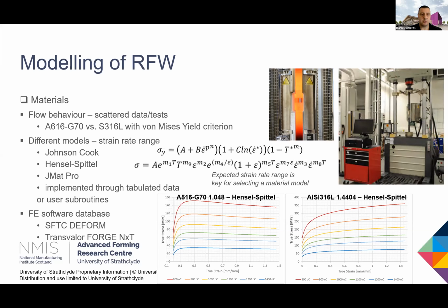However, we can generate material properties from software like JMatPro and implement them through tabulated data or use subroutines. In this specific work, we used information from the software SFTC Deform and also from Transvalor Forge NXT. That was because we could not easily find those specific conditions. We lacked information about the material in the full temperature range, so it became a little bit challenging to model, and obviously we had discrepancies with the trials.